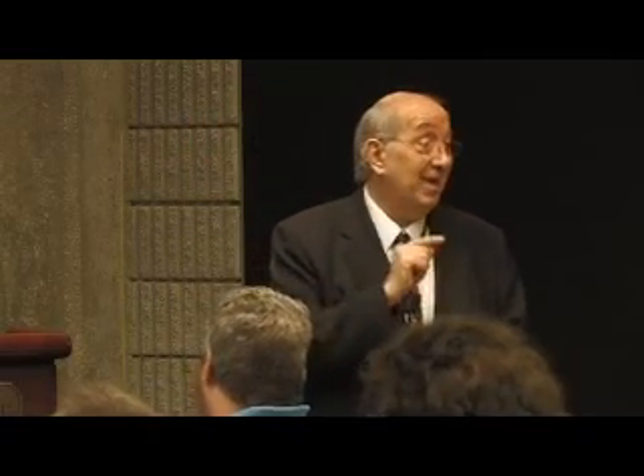How many people today, by the way, are using eddy current to check case depth? Anybody here? Well, if you are, just as a note, or if you're thinking about it, eddy current does work, by the way, but what I've found is that if the eddy current passes, the case is indeed good. But if the eddy current fails, the parts can still be good. That's when I get to cut up more than one, and I like that. I like cutting things up. But eddy current testing today can determine that the part is good, it can't determine that the part is bad. So if you're thinking of that technology, keep that little insight in mind.